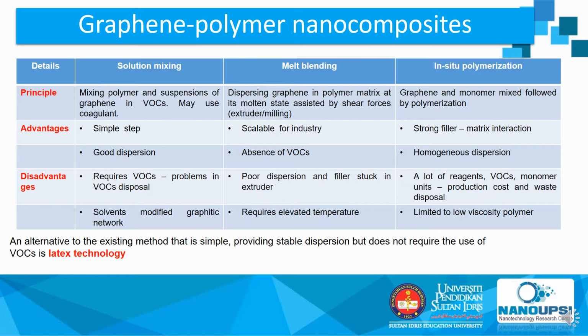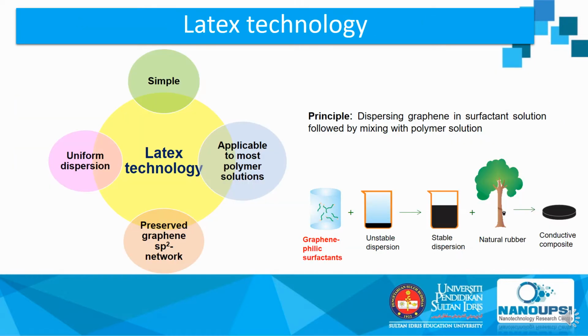So one alternative way to produce graphene polymer nanocomposite is through latex technology. Why does latex technology provide a better technique? Because it is simple and applicable to most polymer solutions. It can preserve the graphene sp2 network and provide a uniform dispersion. In this technique, one of the main components introduced is a surfactant, which helps to stabilize the graphene in the polymer matrix.